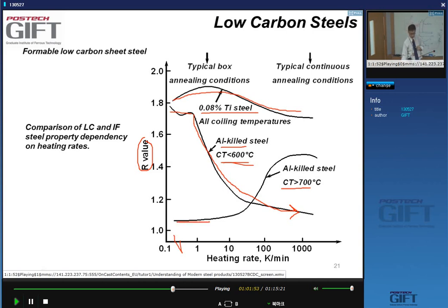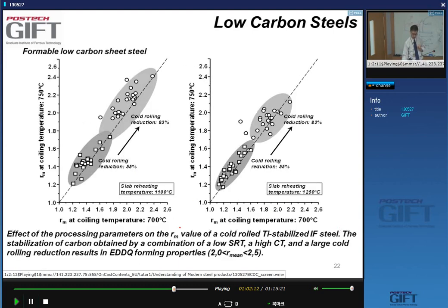With high coiling temperatures, I need to have high heating rates in continuous annealing conditions to achieve a better, not a high, but a better R value.